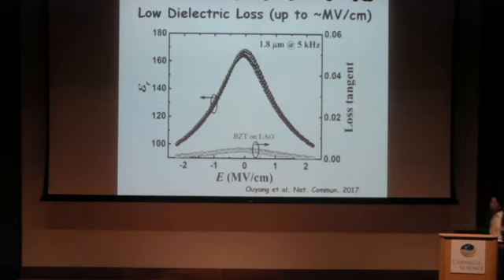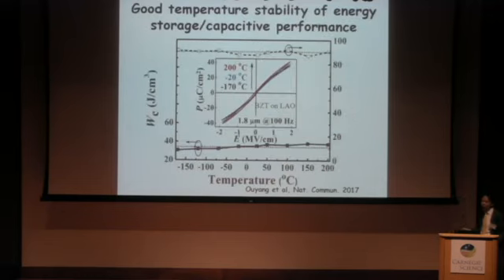And here I show you the low dielectric loss of this nano polydomain film. This is a film grown on LAO. It's about 2 micrometer. We apply basically 400 volts on the film. You can see the loss stays low up to the megavolts per centimeter level. That's good quality film. And we also did temperature stability study.